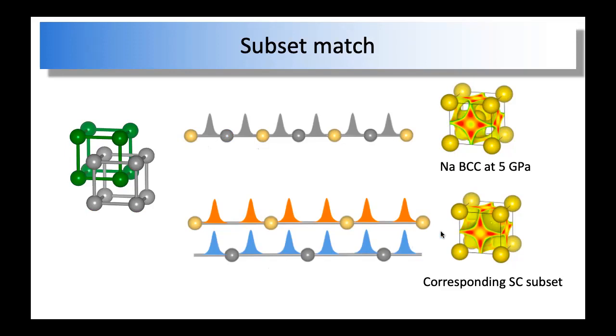You have many possibilities. But for sodium BCC at 5 GPa, if you calculate just for one single cubic, which is a subset of the whole BCC lattice, you find the electron localization falls into the exact same pattern as the original BCC. So now you have electron localization at the exact same location as the overall BCC. Okay, and the same, of course, is also true for the other subset. And remember the midpoint. This is the midpoint. The midpoint for the two subsets are exactly the same points. So this means if you interpenetrate these two simple cubic lattices together, these two electron localizations will match each other exactly. They will help each other, they will like each other, and therefore they stabilize the BCC structure.